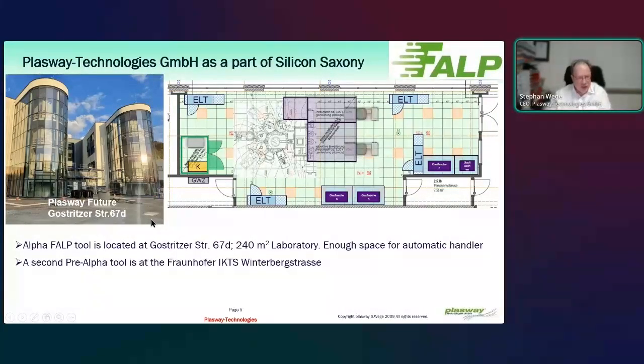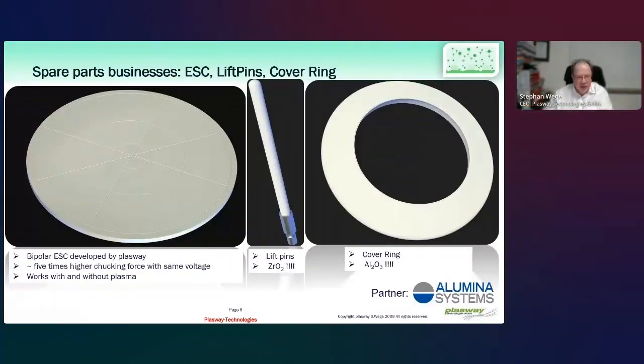We are located in Dresden, in the Gostritzer Straße. We have a big laboratory where we are now mounting a multi-chamber system with a partner, and we just moved in two weeks ago, so this is really the first time that I can give you some insights. Besides our technology, together with Alumina Systems, we provide special parts, especially a bipolar ESC for thermal control on 300mm wafers. We also supply lift pins made of zirconium oxide. I think nobody can really do it at the moment. And we're also building cover rings out of aluminum oxide, as I said, together with Alumina Systems.